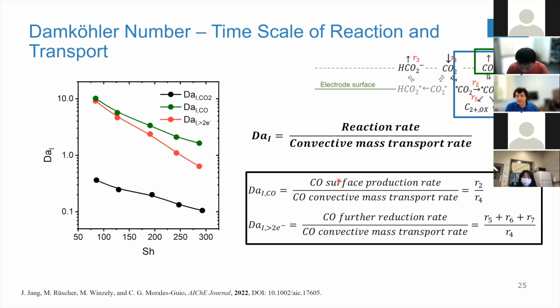When we measured the CO surface production rate, so this is step R2, relative to the transport of CO away from the surface of the electrode, that would be this Damköhler number 1 CO. This is shown here as green. What you see is that these values are all larger than 1. What it means simply is that we make CO at a rate that is much faster than what we can transport away. So that CO accumulates near the surface of the electrode, and then you have a lot of back mixing. And that is what gives us that CSTR, well-mixed volume near the surface of the electrode. And if you look at the further reduction rate, that will be this red line. What we say is that this is actually 1 over Sherwood squared.